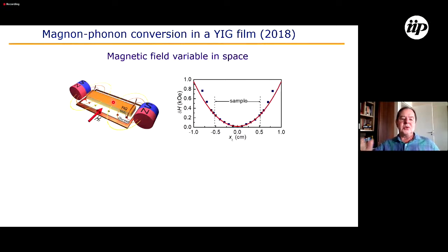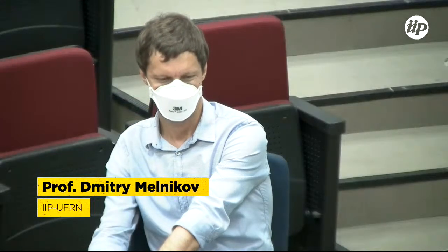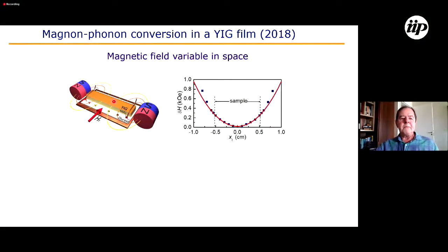Nowadays, we don't use cylinders or rods for making experiments. It's much better to use thin films. 60 years ago, people did not know how to make a thin film. But today, we know how to make a single crystal thin film with a few micrometers or tens or hundreds of nanometers. We have a YIG film, but we want to create a non-uniform field. So to create a non-uniform field, we use two small magnets, rare earth magnets, placed like this.